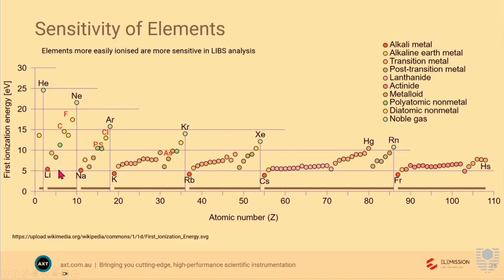And you see here lithium, sodium, potassium, rubidium, they all have very sensitive LIBS spectra. That means you can get really low concentrations, because they love to give up an electron. By the time you get over to the halides, like fluorine, they don't like to exist in the +1 ionic state, so they prefer to be in the -1 ionic state, but you can actually get a LIBS spectra as a molecular line. So for example, calcium fluoride, calcium's 2+, fluorine's 1-. You actually get a molecular line as CaF+. So the elements on the left-hand side are really sensitive.